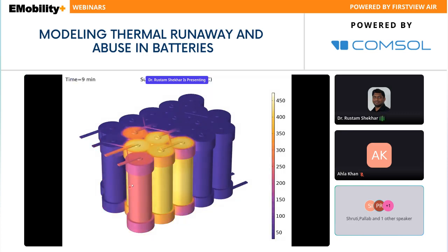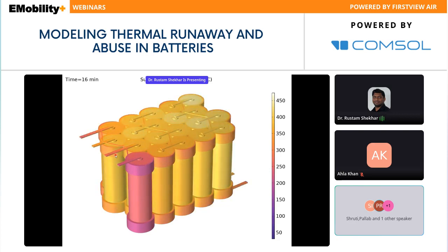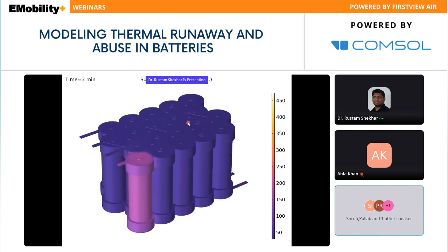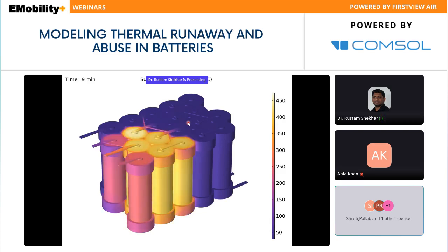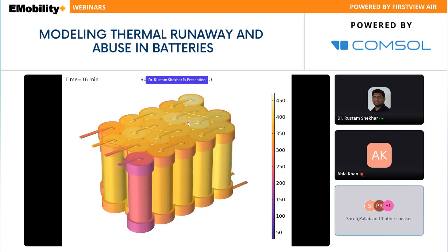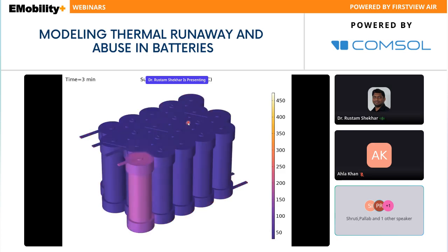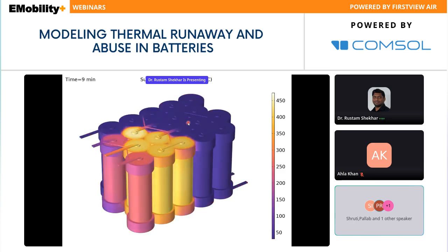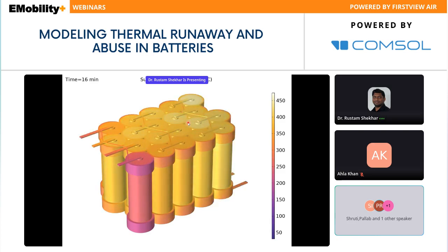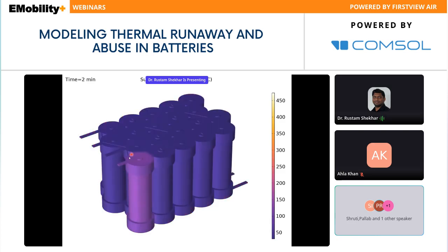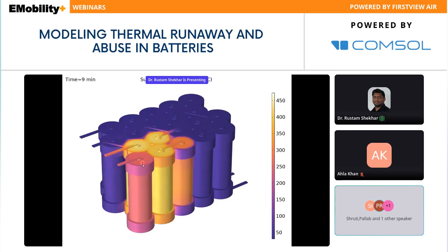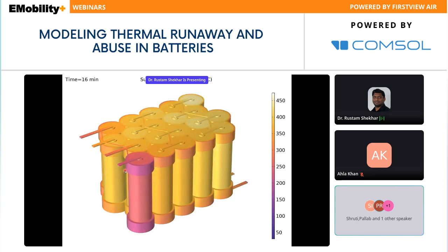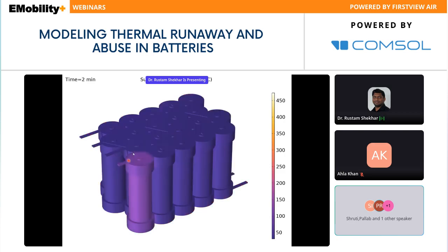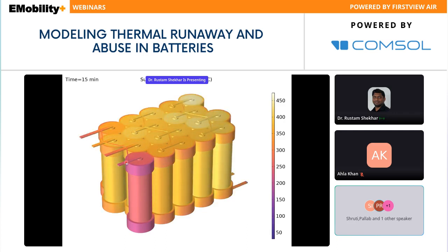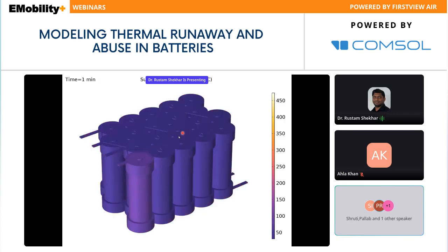Now the first cell is failing, and because of that, you can see it is propagating to the other cells, and we can identify the maximum temperature and propagation pattern. If you want to prevent this, that can also be done in these kinds of scenarios. We can have some kind of wrapping around it, with phase change materials, any filler material, or decoupling the cell when it gives you the alarm of the failure. Then all those strategies can be taken, and you can design your thermal runaway scenario.